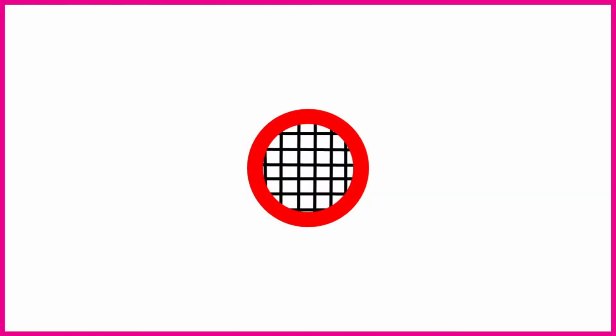Now, as you can see from the image, Biax glass features glass running in two directions, at 0 degrees and 90 degrees. These add strength along both the length and the width of the board. However, because the reinforcing is only running across the length and the width, it's not adding much resistance to the torsional twisting. And that's the reason why you see Biax glass used on boards that have a softer or more playful flex. By reducing torsional rigidity, you're going to allow the board to twist, creating a predictable and easier ride.